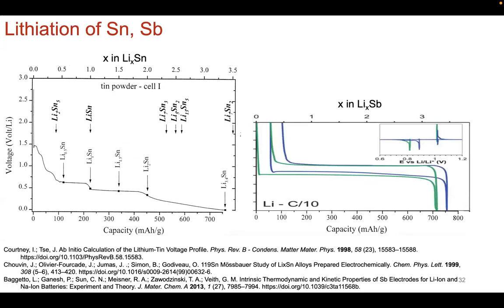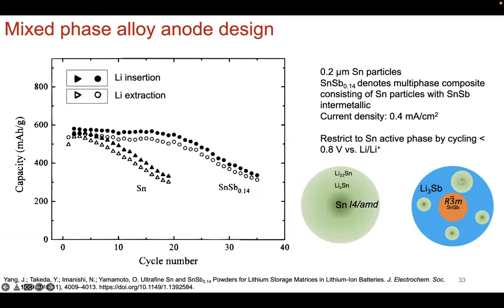And so if you look at the end members, if you only lithiate tin or only lithiate antimony, what you see is exactly what mirrors the expected phases for the phase diagram. You see here the two-phase coexistence, these plateau regions, and in antimony, you see exactly that, the formation of Li3 antimony. Okay, so that's for the end members. Now, if you then start mixing this two-phase composite region, let's say this tin antimony, what you get is increased capacity in the two-phase mixed composite versus the end member. So you can see here on the x-axis is the cycle number and the capacity retention is on the y-axis. So you can retain the same amount of capacity, but over a larger number of cycles.